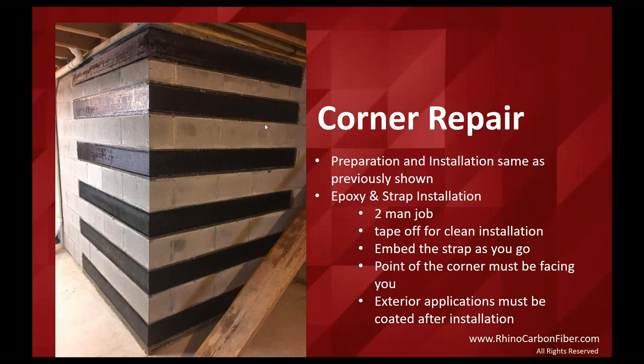So the prep work again will remain the same. You're going to grind the surface, fill in any mortar joints that are low, repair any cracks. To achieve a corner repair that is this great, it's going to be a two-man operation, and it's going to have to be Gorilla tape on the edges, and plastic off between it. The reason this is a two-man job is the only way to keep it clean is to have one guy applying the epoxy, and the next guy standing right beside him troweling that epoxy out and immediately laying the fiber in. Working with it horizontally like this, the epoxy wants to run. If you don't have somebody immediately troweling it out, it's going to run down the face of the wall.